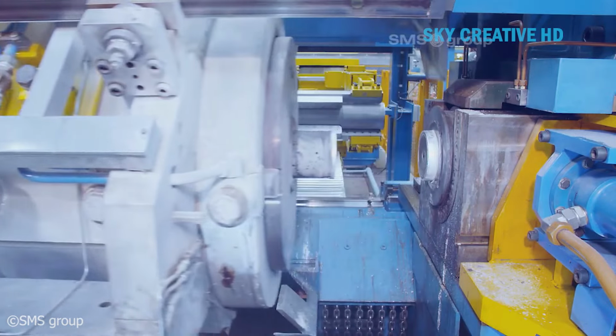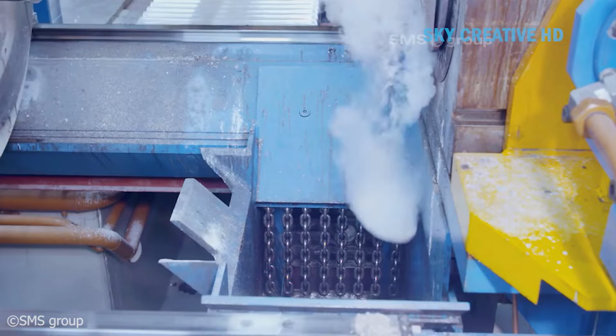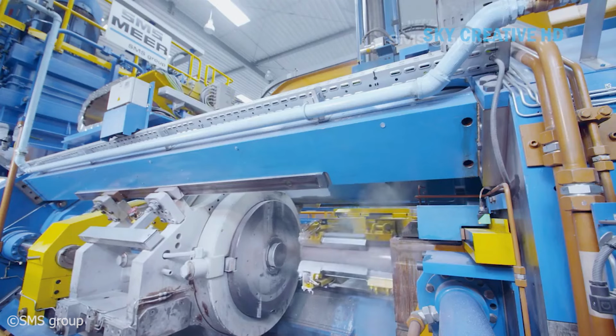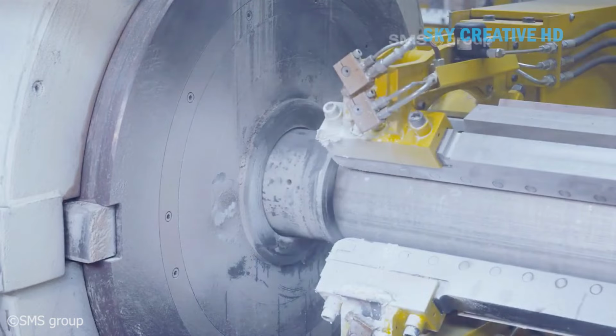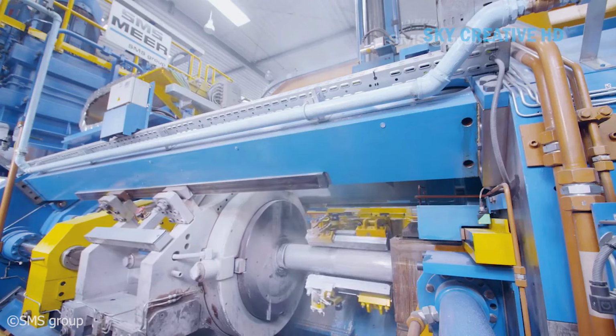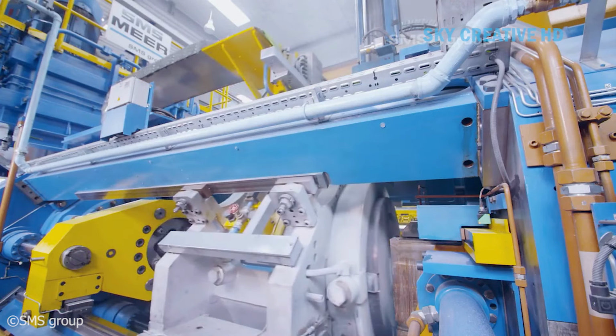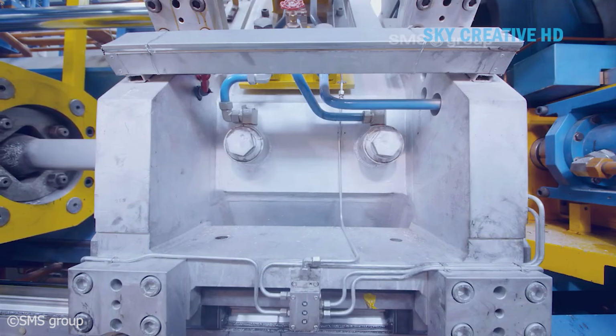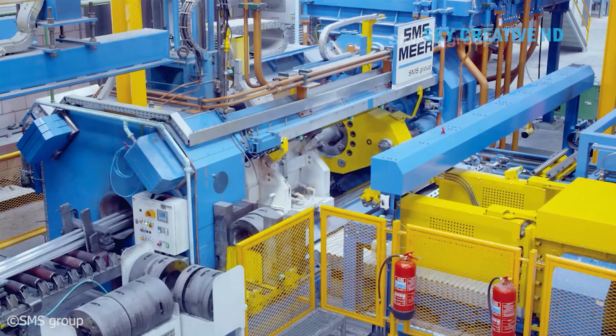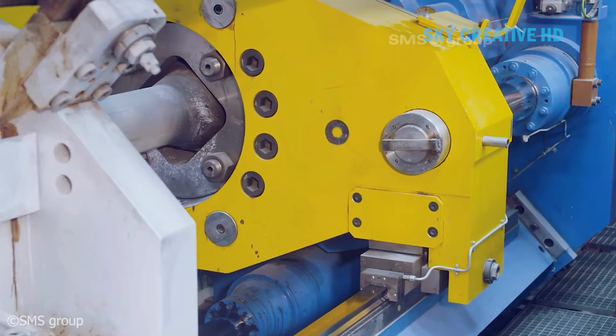The die itself is an engineering marvel, precision machine tool steel with openings that create the desired profile. Whether it's a complex hollow shape or a simple angle, the die determines the final form. As aluminum flows through at speeds up to 40 feet per minute, it emerges on the runout table, where powerful fans and water spray systems immediately begin cooling the profile. A puller grips the leading edge and maintains consistent speed through the process.